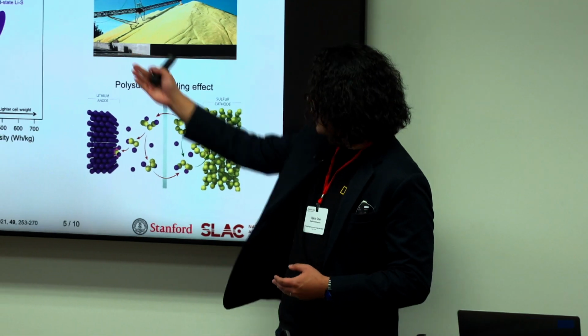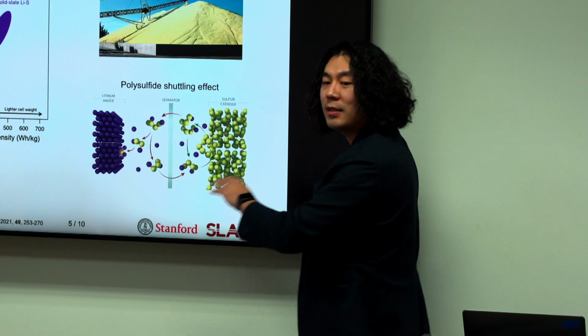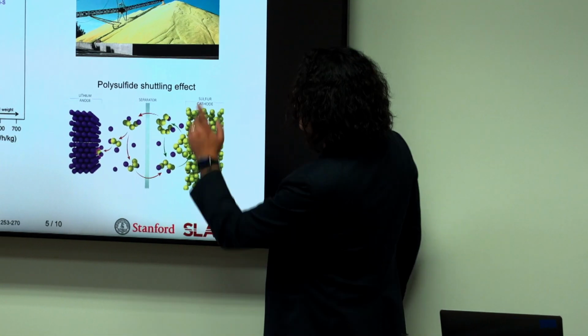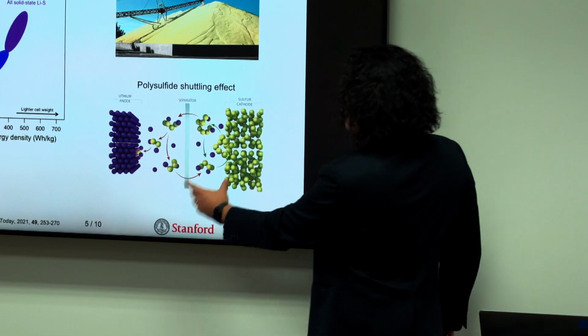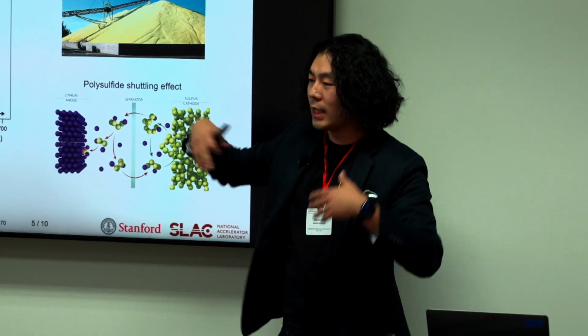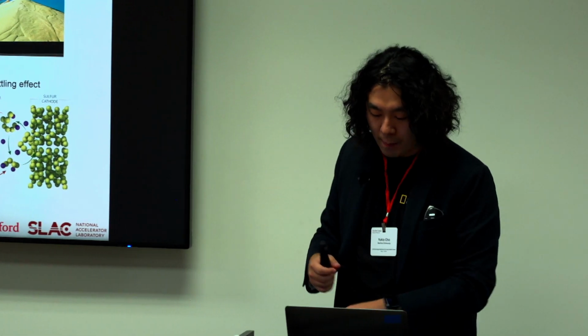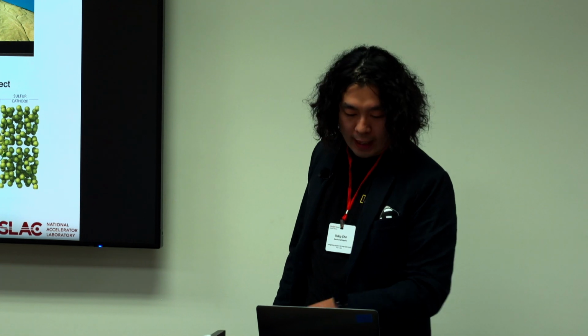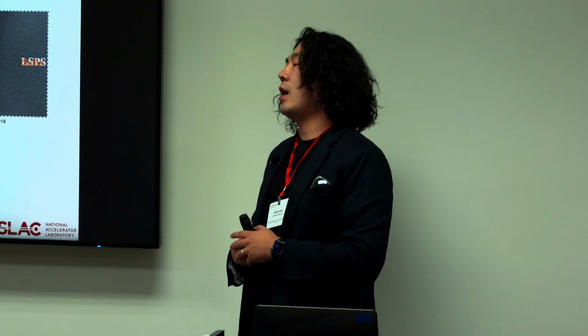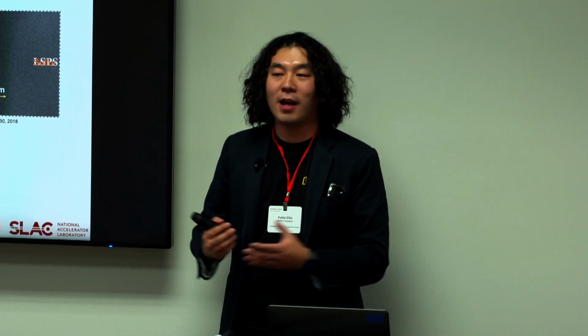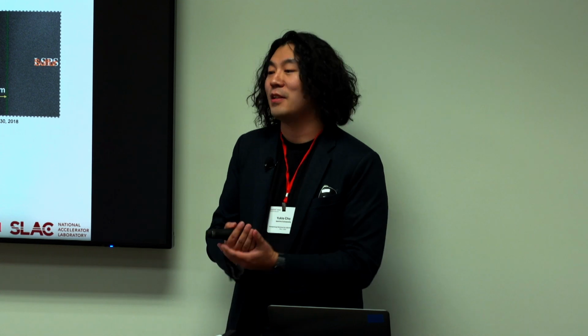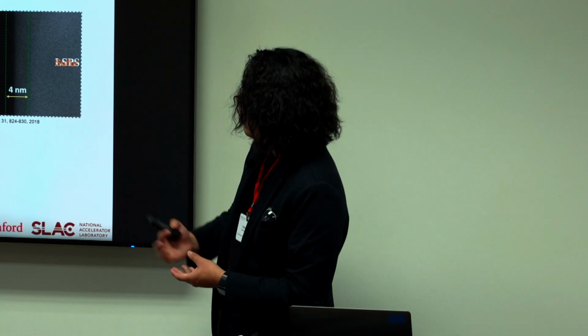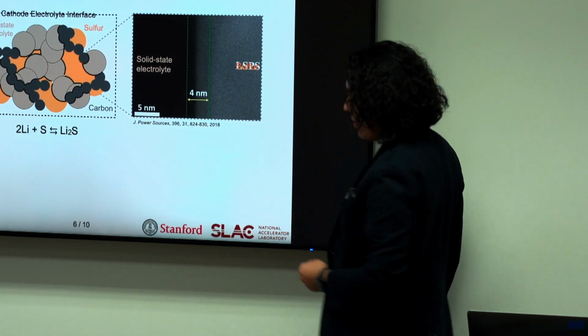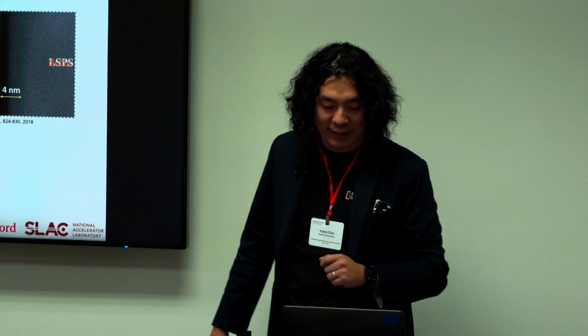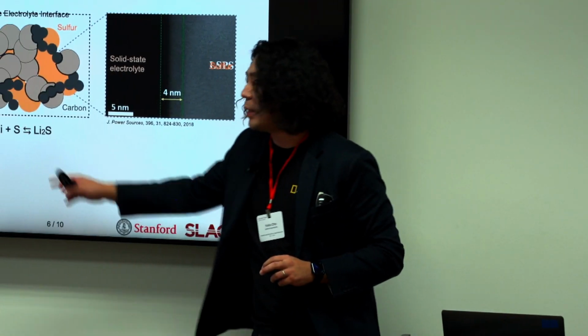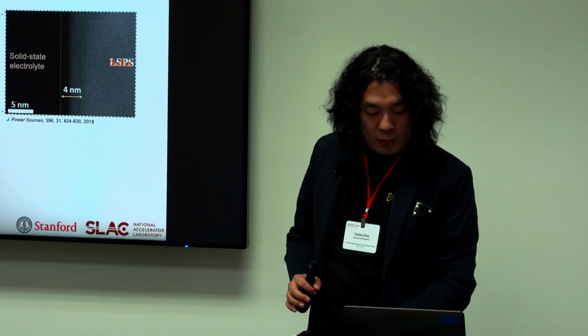So my proposal is, instead of using liquid, let's use something that completely blocks this intermediate compound, which is all solid state. So completely here is going to be solid state. As you can see, not only can you expect a little bit higher energy density, but potentially you can completely prevent this effect. The proposal here is, well, this thing is not there yet. It's mainly because the interface or the kinetics is not doing a good job. As you can see here, everything is happening in this very thin layer of interface, as we have been discussing the whole day. And for the reaction happening, this solid state setup is just not doing a good job.